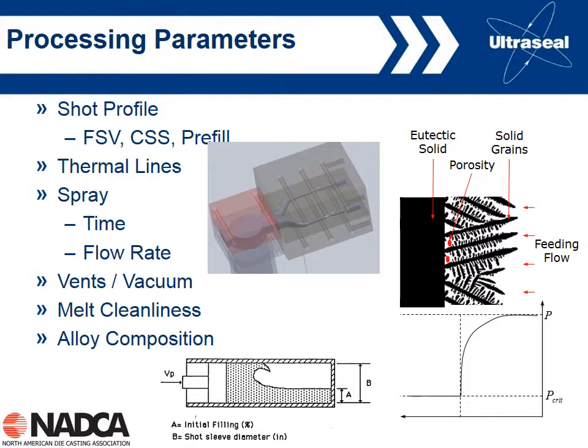And so for narrow freezing range alloys, we tend to get larger pores, which are generally easier to detect on X-ray. With a wider freezing range alloy, we get smaller, better distributed pores. Still there, we're still getting the same amount of porosity, but it can be more difficult to detect on X-ray. But alternatively, it could create more of a problem if you've got a pressure type part. So those are some of the things you've got to think about, and we'll talk about that a little bit later on in today's webinar.